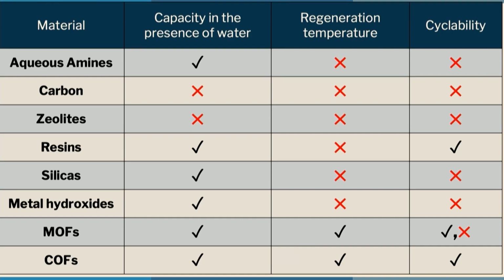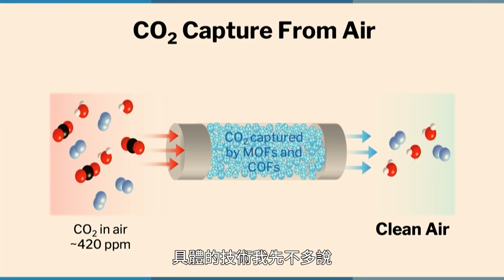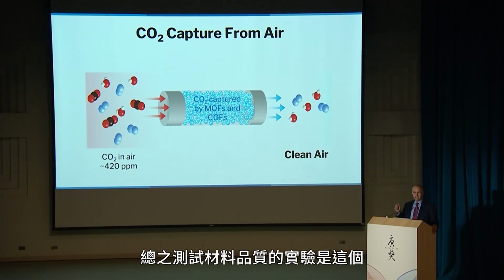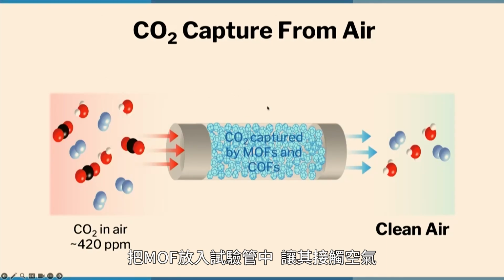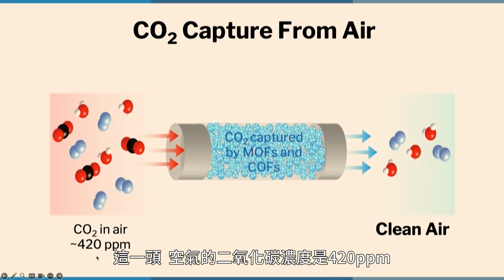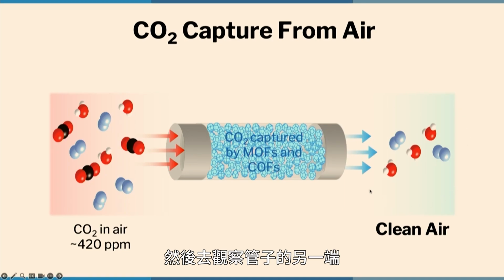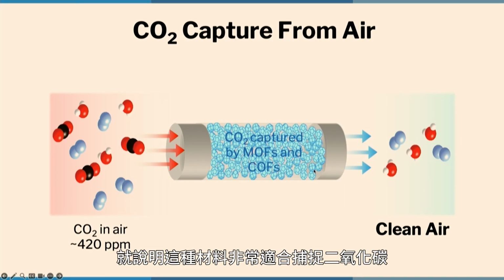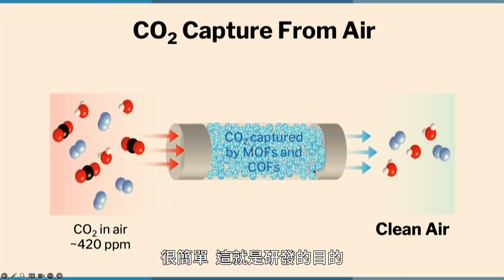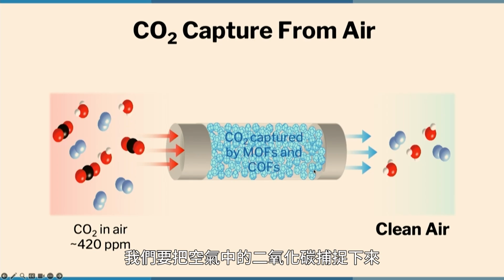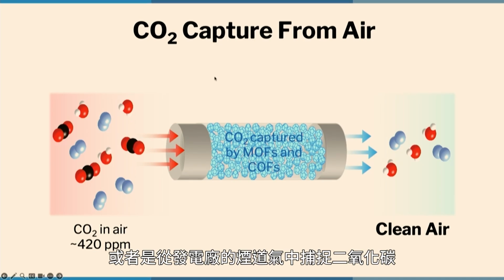So without going into the technical details, the real experiment that indicates whether you have a good material or not is this one. You put your MOF in a tube and you expose it to air. Here's the air at 420 ppm, okay? And then you look at the other side. If the other side doesn't have CO2, then your material is great at capturing CO2. Very simple. That's what you want to do. You want to scrub the air of CO2, or this could be flue gas from a power plant. You want to scrub it.